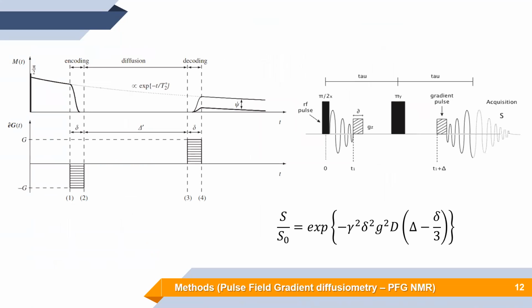In terms of pulse field gradient diffusometry NMR experiments, it is an experiment which allows us to trace the translational motion of the species that we are interested in. For most of the cations, as we are talking about ionogels, there are protons in them, so it is very easy to follow with NMR. And in most of the anions, we found other NMR active nuclei, which also can be registered. So in principle, with this pulse field gradient diffusometry, we are able to trace the movement of the spin system of the particles which we are interested in and observe the attenuation of the signal caused by the translational motion.